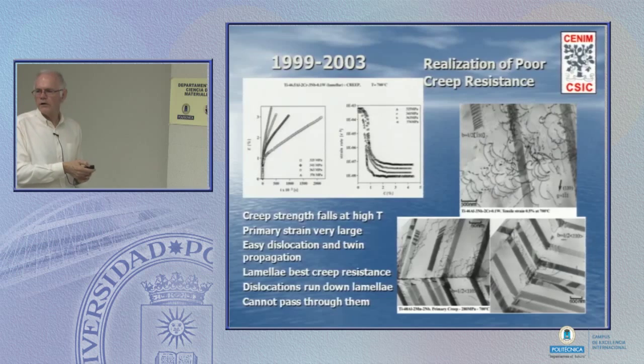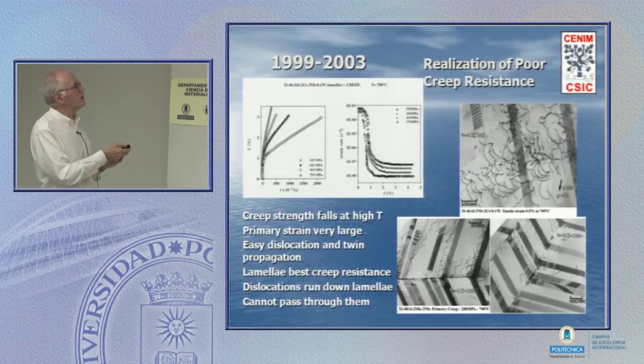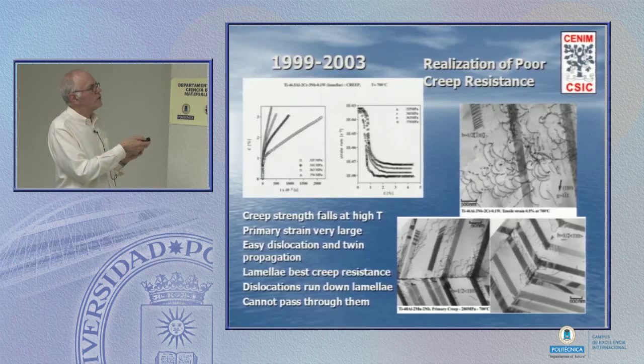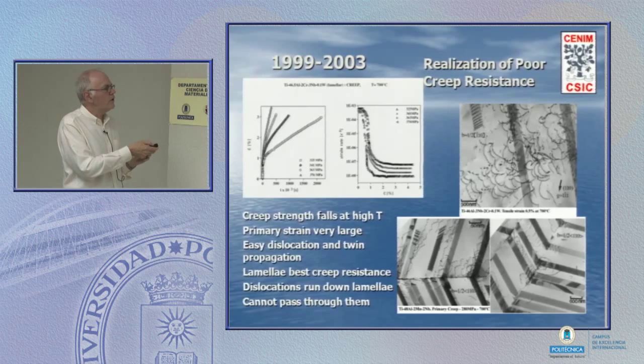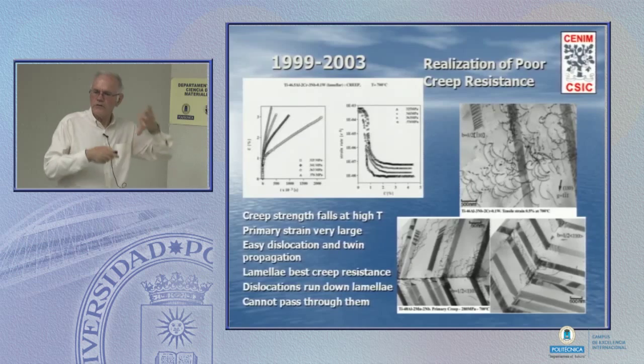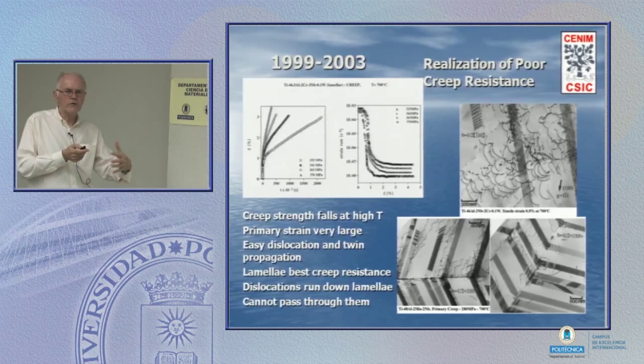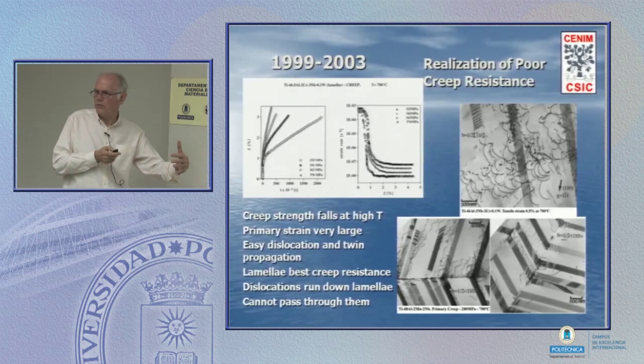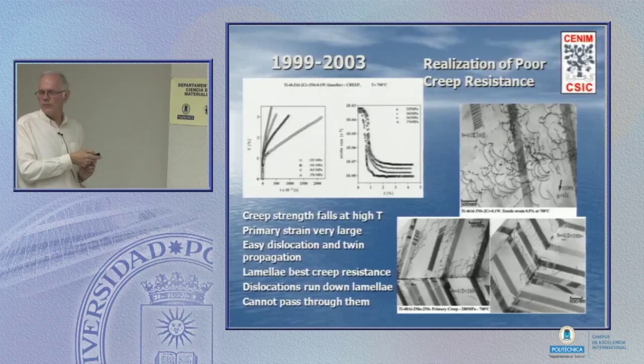The creep problem has been a great problem after having developed alloys and structures that had suitable strength and toughness and so on. For the reason that we see here, we're looking at the creep rate as a function of time or strain. We're creeping at 700 Celsius. Let's add a stress of something like 300, 350 megapascals. What we see is that the creep rate is enormously high for something like 1% strain, and then the material work hardens and the creep rate becomes acceptably low. But of course, if you think of a turbine blade that's spinning inside a container, what we cannot do is to allow this component to stretch 1%. It's too much. And so avoiding this primary creep strain has been a great problem.